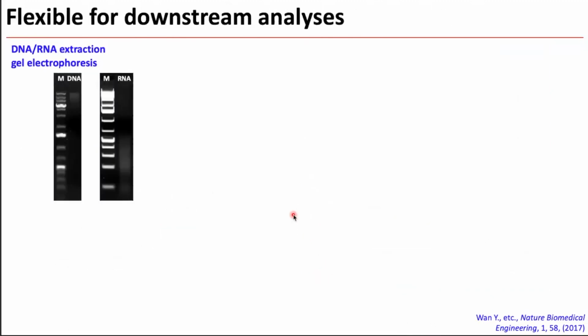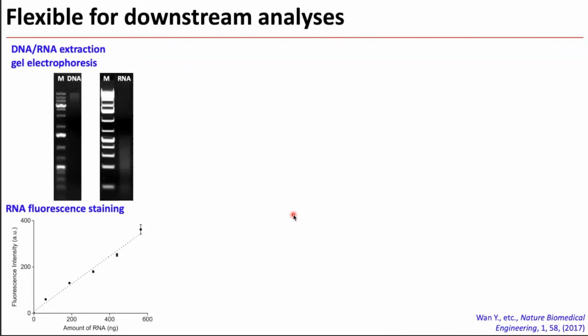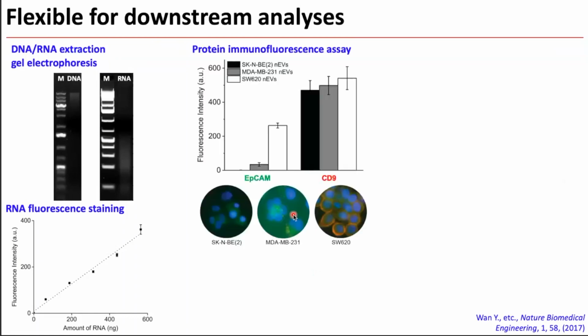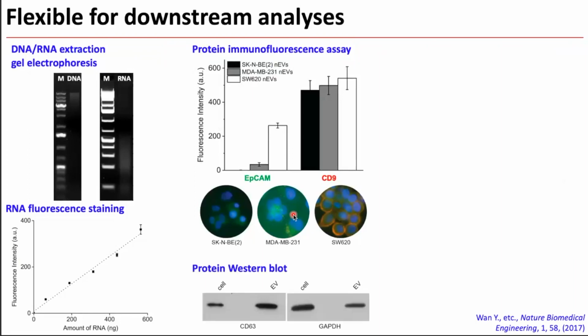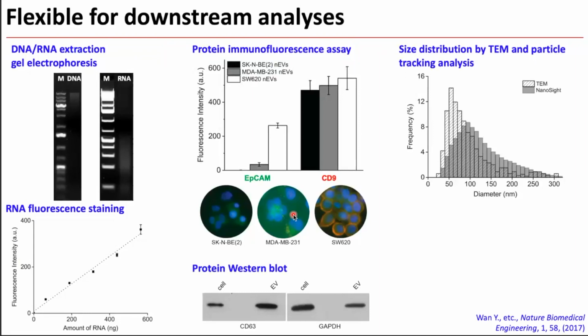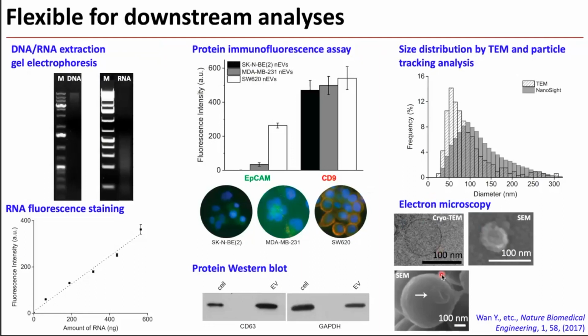And then what we do is we actually use a variety of downstream analysis methods. So for example, we can extract the DNA and RNA and run electrophoresis. We can use RNA-specific fluorescent dye to stain the RNA inside those vesicles and quantify the RNA amount. We can also run protein immunoassay and basically show the protein content of the vesicles is consistent with the cells where they're derived. And then, of course, we can run a Western blot. We also use TEM and particle tracking analysis, NanoSight, to characterize the size of the particles isolated using this technology. We also use a variety of different EM technologies to visualize those isolated vesicles directly.